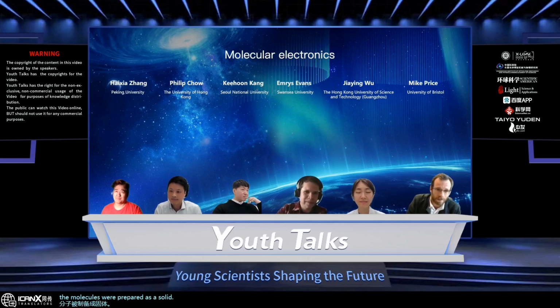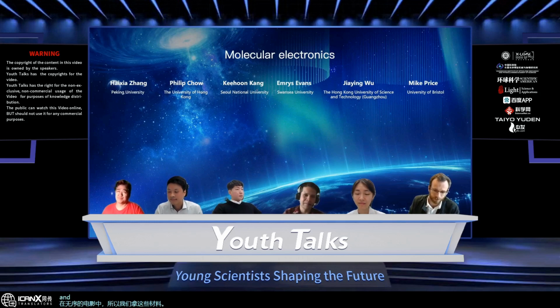Yeah. So those systems I was talking about at the end of the talk. So we are studying them in disordered films. So we take these materials and we spin them in PMMA, so polymethyl methacrylate, and we made some, quite basically, when you have a material and you want to make a film, it's the kind of first thing you try. So they were disordered films, and so when we were looking at trying to study their magnetic response with light,